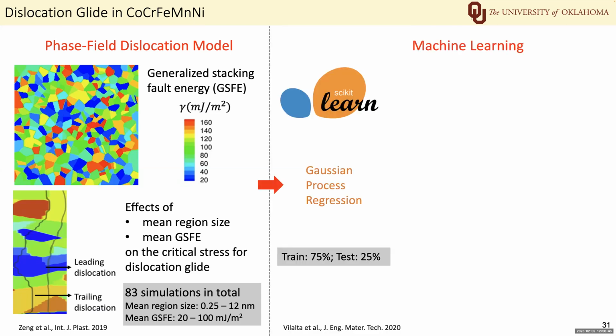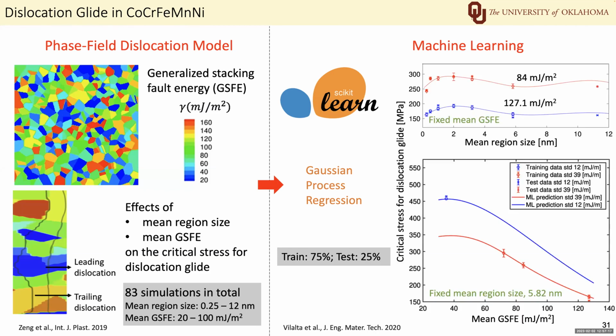So one way to link the input and the output is machine learning. So we use Gaussian process regression, an algorithm that is implemented in scikit-learn. We use 75% of the data to train the machine learning model and 25% for the test. We find that the mean GSFE affects the critical stress for the dislocation glide much more than the mean region size does. Therefore, to achieve MPEAs with high critical stress, we mainly need to change the mean GSFE from the perspective of alloy design.